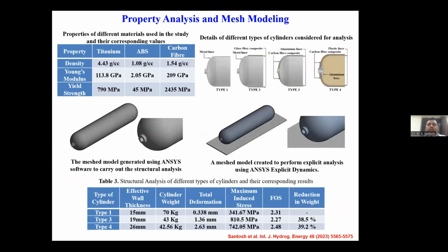When I was talking about type 4 hydrogen cylinders, there are 4 different types of cylinders that are identified in the commercial sector. Type 1 is a metallic liner, which doesn't have any kind of overwrapping on it. It can be either steel cylinders or aluminum cylinders. And it can also be overwrapped with some glass fiber composites, which is called type 2 cylinders. And subsequently, aluminum liner material or titanium liner materials overwrapped with carbon fiber composites are termed as type 3. And finally, a polymeric liner material, which is encompassed or covered with a carbon fiber composite, is called type 4.